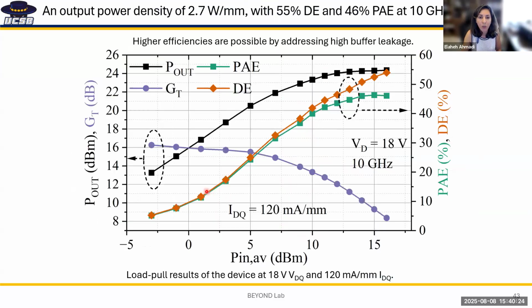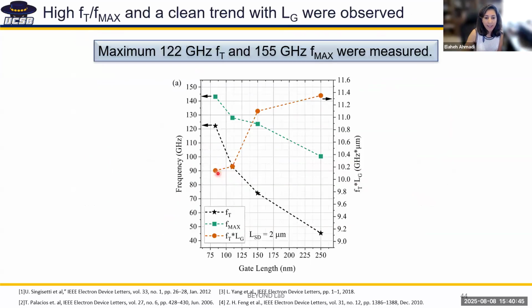but then we were also able to do power measurements, and we showed an output power density of 2.7 watt per millimeter with 46% PAE at 10 gigahertz on nitrogen polar GaN HEMTs. And this is basically different devices on the same epi with different gate length, showing that fT and fmax are scaling with the gate length.